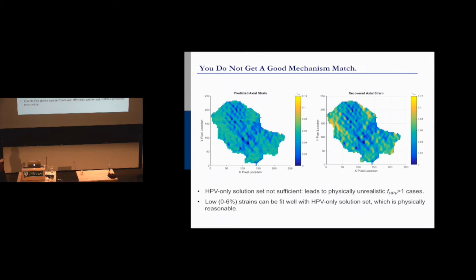And when you do, the match is terrible. It sucks. And the problem is, it didn't work at all. We weren't able to match. This is the theoretical, by saying that it has to be these tetragons, and this is the experimental. And we had really, really high strains in the experimental that we simply weren't able to match by any combination of correspondent variants. We just couldn't get them to work. We could match the low strain regions really well, but we couldn't get the high.